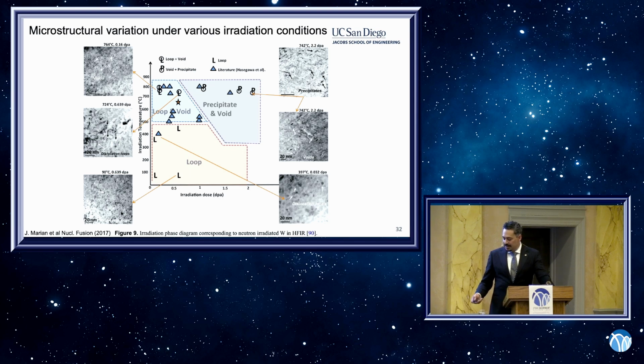So a large void formation is a major problem. If you look over here, on this side, at larger doses, you get not just the dislocation loops and the voids, like we already talked about at these lower doses and higher temperatures, but we also start getting some precipitates formed. And this is for a relatively pure tungsten material. These precipitates are actually caused by transmutation, the material changing because of the neutron exposure. So tungsten transmutes, changes to other elements near tungsten like osmium and others, and those different elements, as they diffuse around the matrix, cause these precipitates to form. Those precipitates are again a problem because your material is no longer the material that you started with, a major problem.